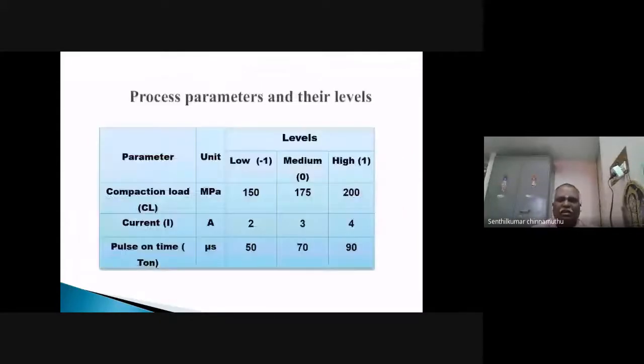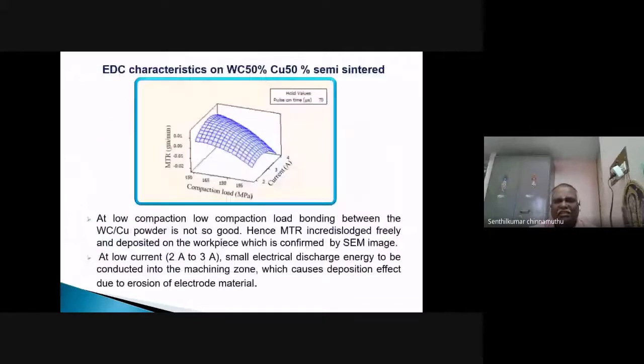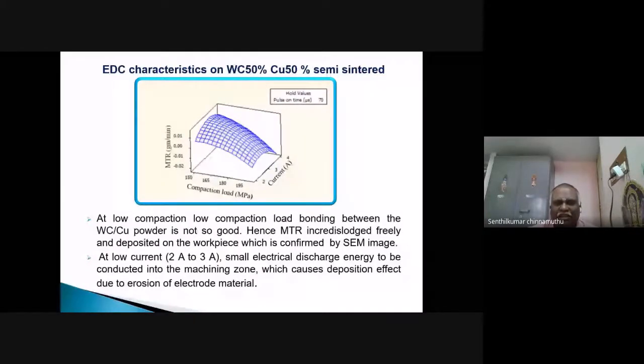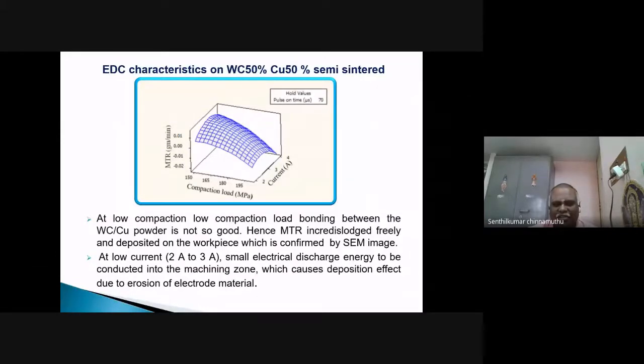See, the graph shows the EDC characteristics on tungsten carbide 50% and copper 50% semi-sintered composite. You might have seen that compaction load and current. The surface plot shows compaction load and current with the effect of MTR, the material transfer rate: how much material is transferred on the surface of the material using compaction load